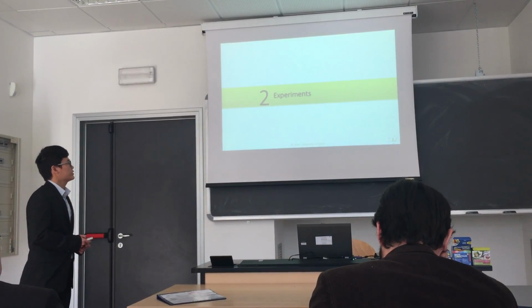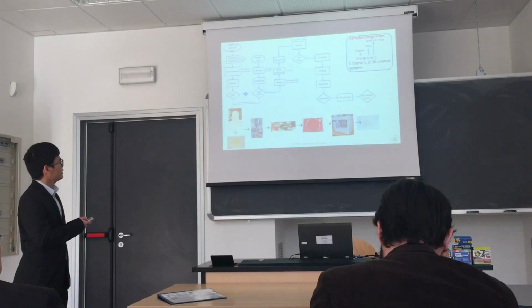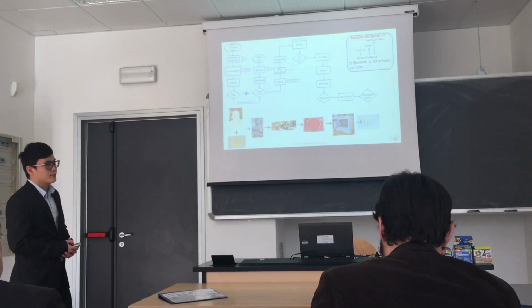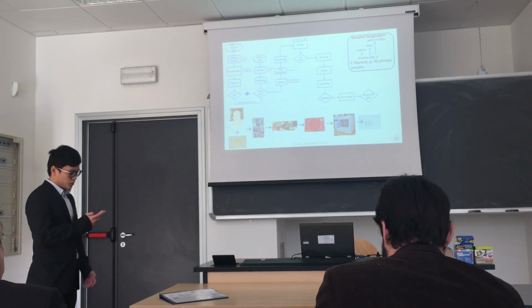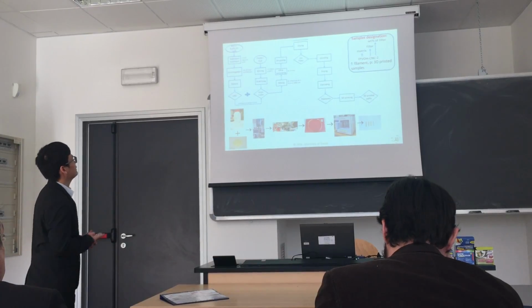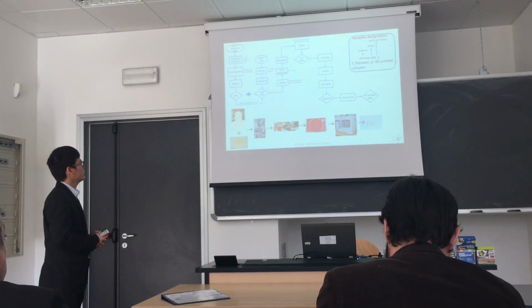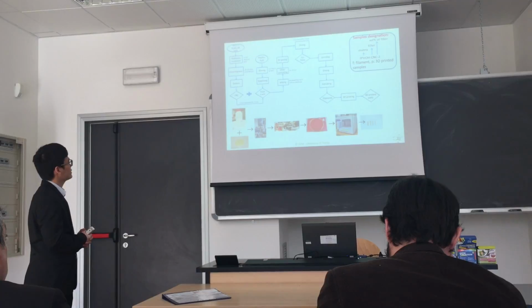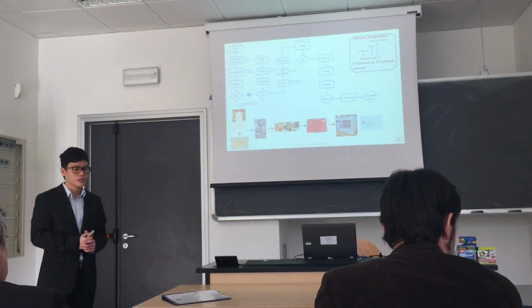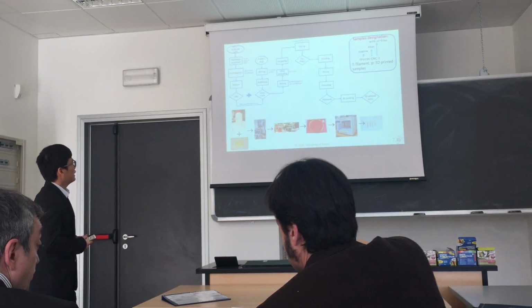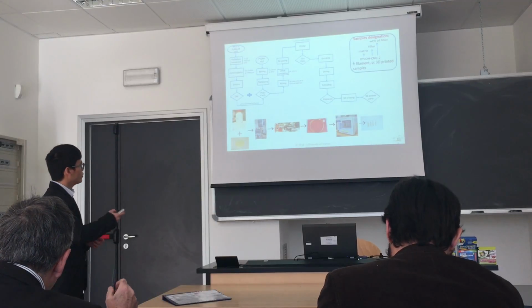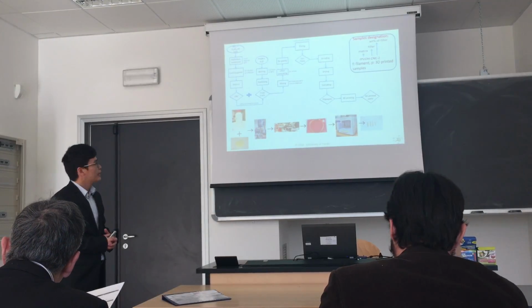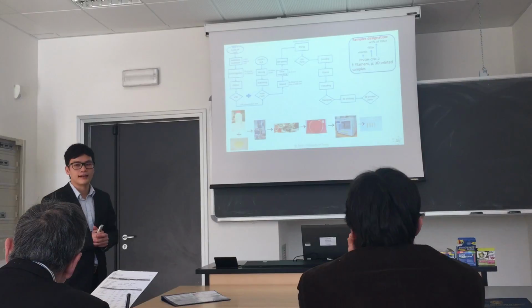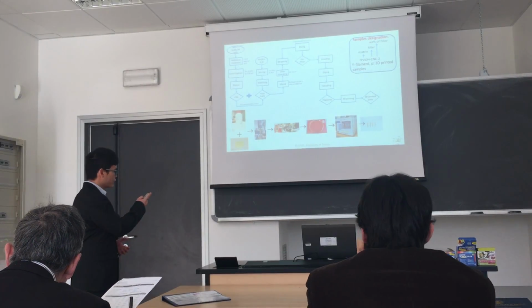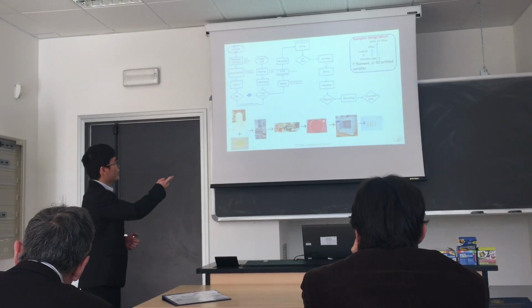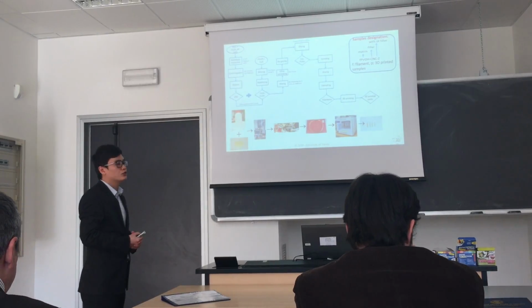Let's move to the second part, the experiment part. Here is my nanocomposite production. You can see here, from the left side, is the production of the nanocellulose. So nanocellulose CNC was synthesized by the acid hydrolysis treatment for 1 or 2 hours. And the synthesized CNCs were then mixed with the PHB matrix with the help of ultrasonication. And the mixture here will then be degassed and dried in the oven for a few days to obtain the film